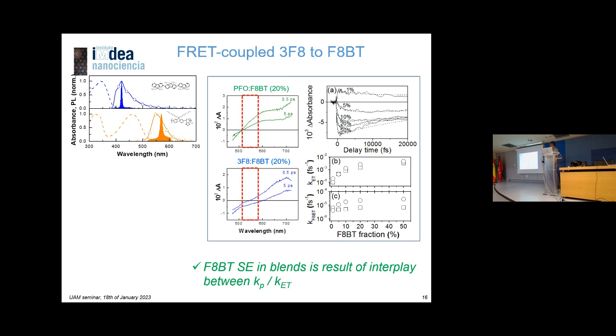If you do a pump-probe measurement, this is what you'd get with the long chain: a positive change in absorption, meaning excited state absorption. Going to the same region, you can see that as you go from 0.5 to 5 picoseconds, there's a change in signal, meaning stimulated emission. So it really works to disentangle the stimulated emission from this problem.